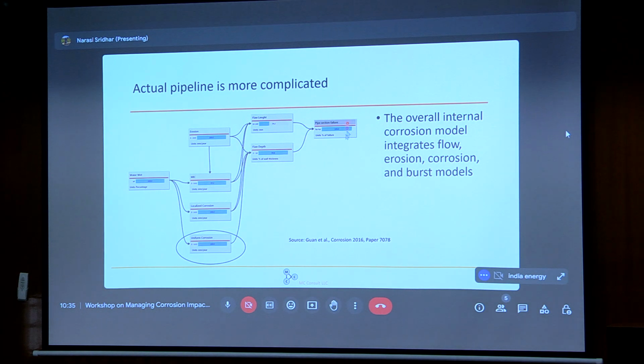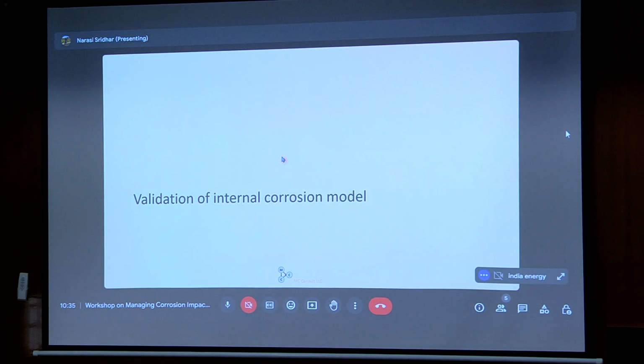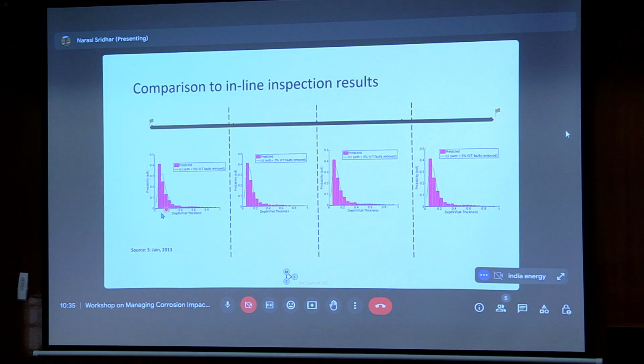And eventually, you're interested in ultimate failure of the pipe, so there is a fracture mechanics component involved in it too. So we can go through these models, and what we have to ultimately do is ask how valid is this model, and we can test it. So here is a pipeline in China where we tested the model, and the pink bars are the predicted probability distribution, and the line is the actual inspection data, and there is reasonable agreement between them. So the idea with these kinds of models is, as you integrate these diverse tools, you have to constantly validate